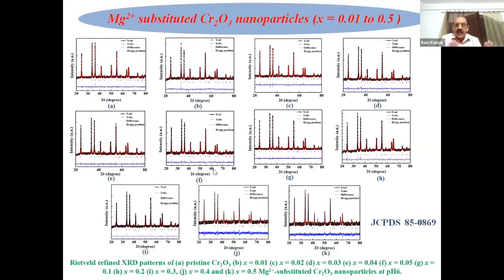Again, X-ray diffraction for a magnesium doped system, magnesium substituted system, up to x equal to 0.5 in this structure, like 25% of that doping is there. All the materials are single phase, no structural change there. And they are very nicely analyzed by Rietveld analysis, and we can find out the lattice parameter value, then chromium oxygen bond length, bond angle, everything we can analyze using Rietveld analysis, and then we can find out their size using the Scherrer relation, and we can calculate the strain in the system. So those parameters we can do.